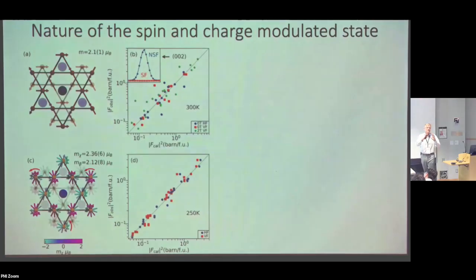And this we saw very clearly because suddenly there was that component that you didn't see when the red trace now suddenly appears. And so we know that the spins are not only rotating in the plane, but they are also oscillating out of the plane. And we have a pretty good determination of that structure. It's actually easier to determine this structure in a sense than this structure, because in this case, the Bragg peaks move away from the nuclear Bragg peaks, and then you can suddenly do it.